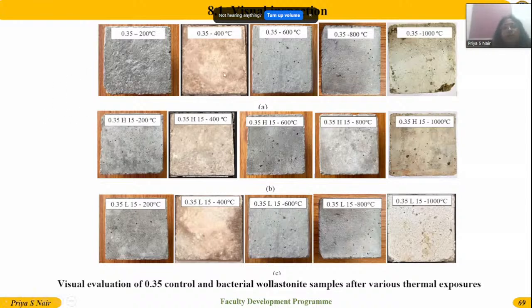So it was seen that at 400 degrees Celsius the reddish color was noticed, and after that the concrete showed a brownish color at 600 to 800 degrees Celsius. Sorry, not brown, gray color, and at 1000 degrees Celsius it was a buff hue. When we see visually, at 1000 degrees Celsius the control samples have shown minor cracks. Others, in higher or lower concentration, showed some minor cracks, but in higher concentration there were no cracks visible. So we can say that it is due to the ability of the higher consortium along with the wollastonite mineral, because the wollastonite mineral has higher thermal stability.